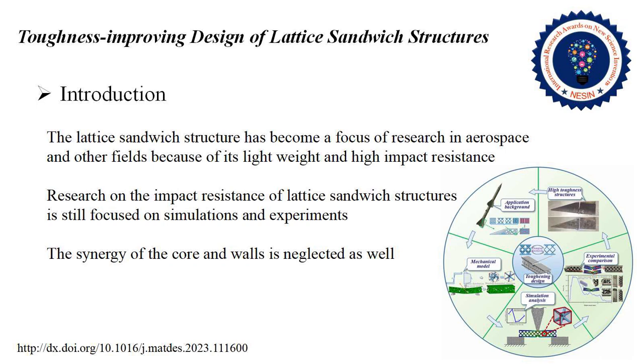Some researchers demonstrated that the strength of lattice structures can be enhanced effectively by preventing the buckling of struts. Some researchers noted that the property of energy absorption for lattices is mainly reflected in the plateau stress stage. Some researchers established a theoretical model of a sandwich plate with a tetrahedral lattice core under compression and shear loads. Some researchers found that the stiffness and energy absorption capacity of lattices can be improved by a reasonable gradient of relative density, and some researchers proposed that the compressive strength, plateau stress and energy absorption of lattices can be enhanced by a dual-phase structure with an appropriate reinforcement phase.